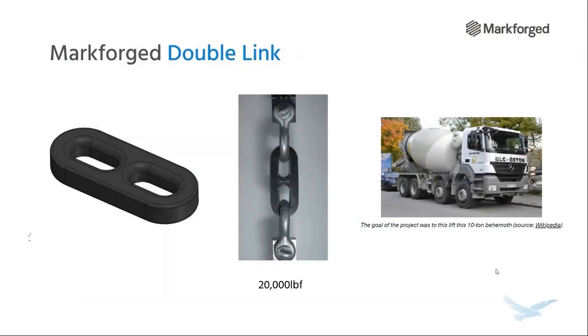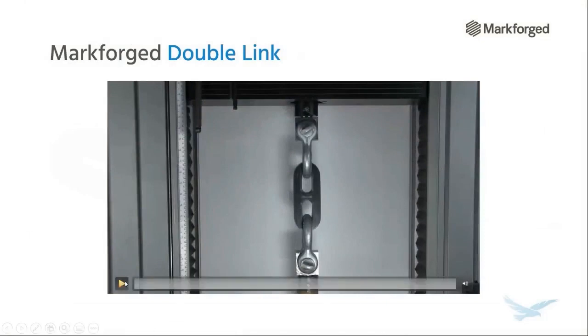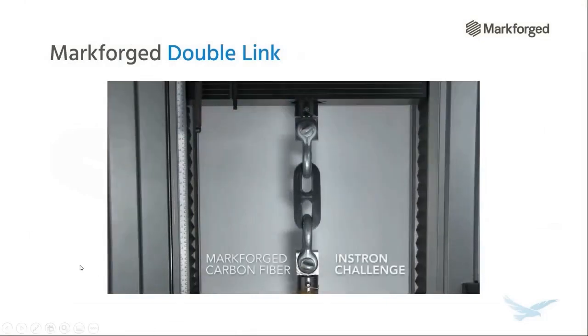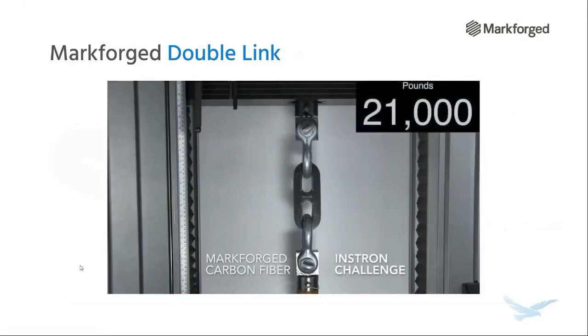And I want to show you the tensile test. So they actually tested this part for maximum strength, and the results are amazing, really. And we'll see. So 20,000 pounds, 10 tons. Let's take a look at the tensile test. So here we have the part that's constrained on the bottom. The part's being stretched on top. And look at that, we're over 21,000 pounds now, about to reach 22. It's getting pretty close.